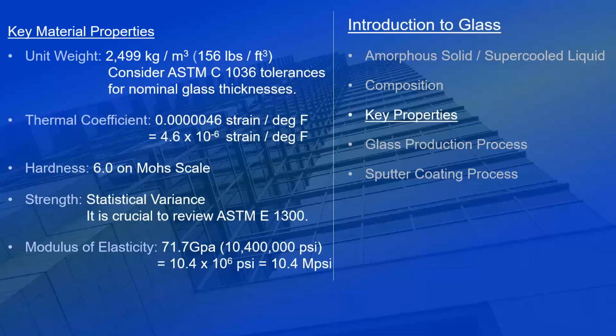The float bath process involves the glass batch, or the glass mix, being gently cascaded onto the top of molten tin. If we think of concrete with a density of 2,400 kilograms per cubic meter, molten tin has a density of about 7,200 kilograms per cubic meter, so much more dense, thus allowing the glass to float on top of that molten pool of tin.